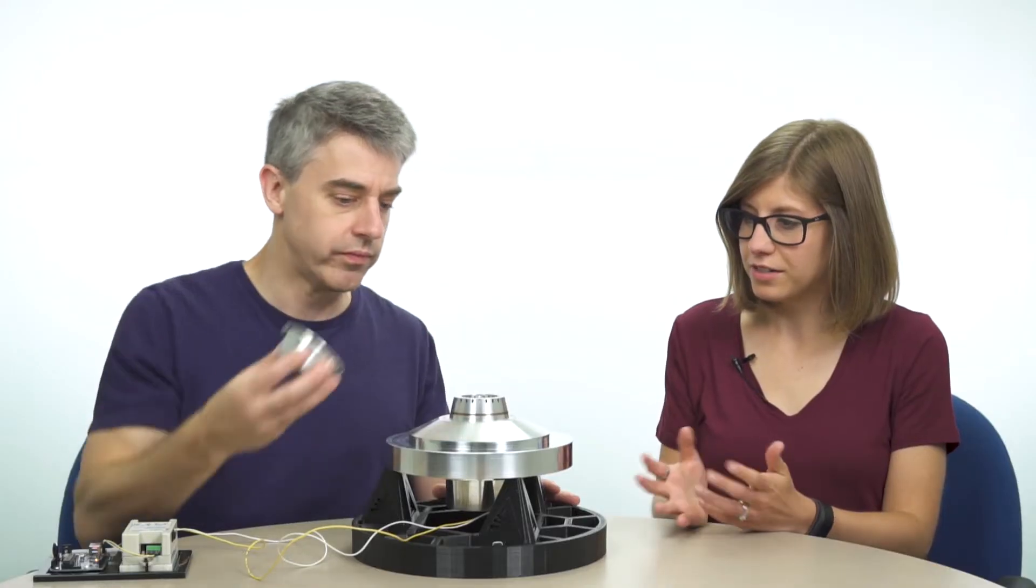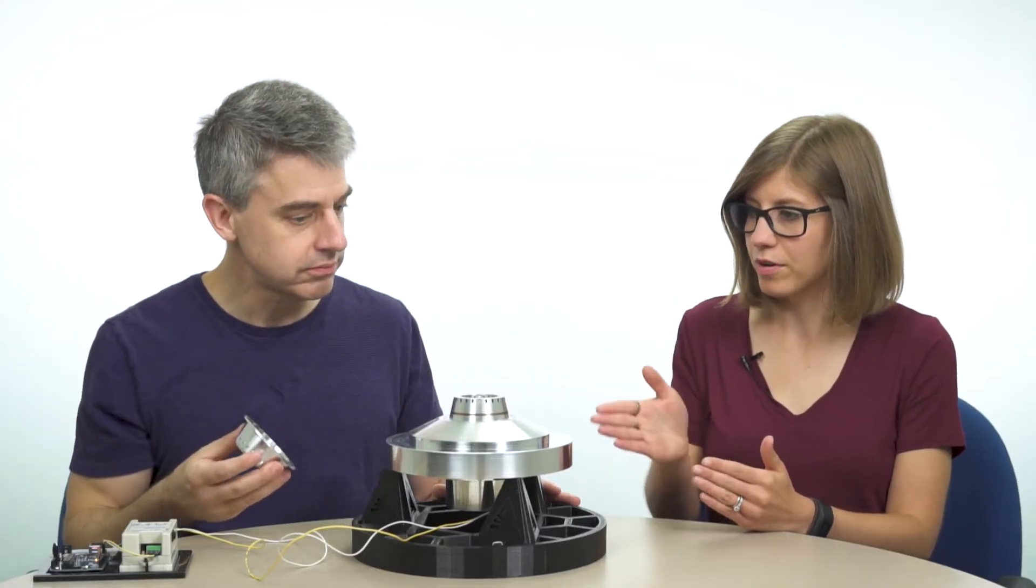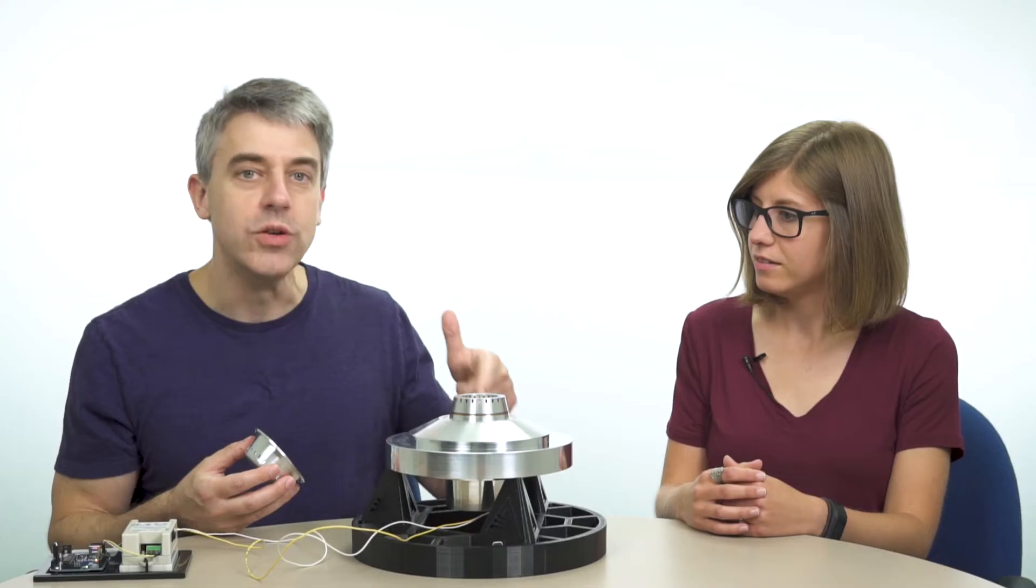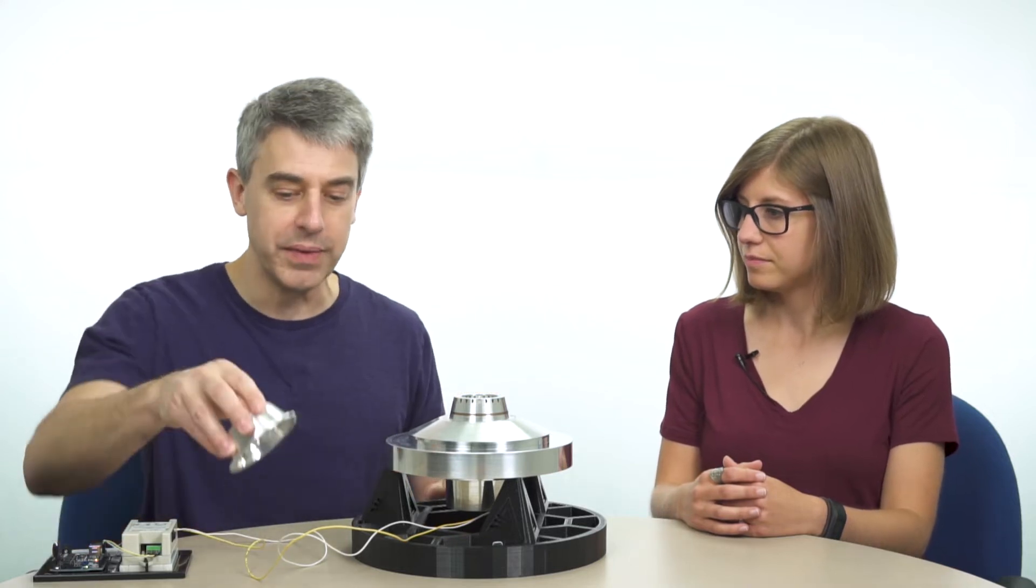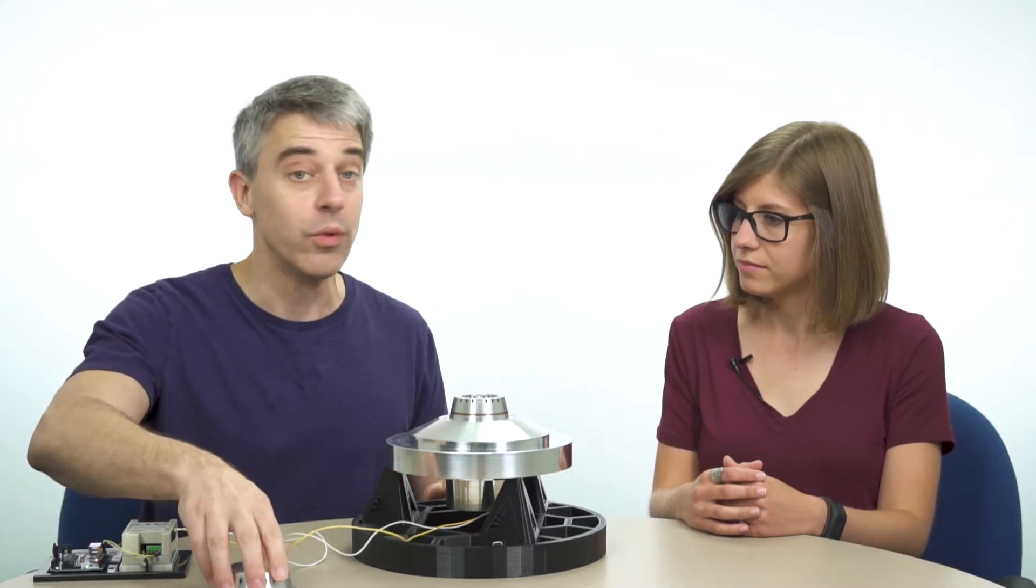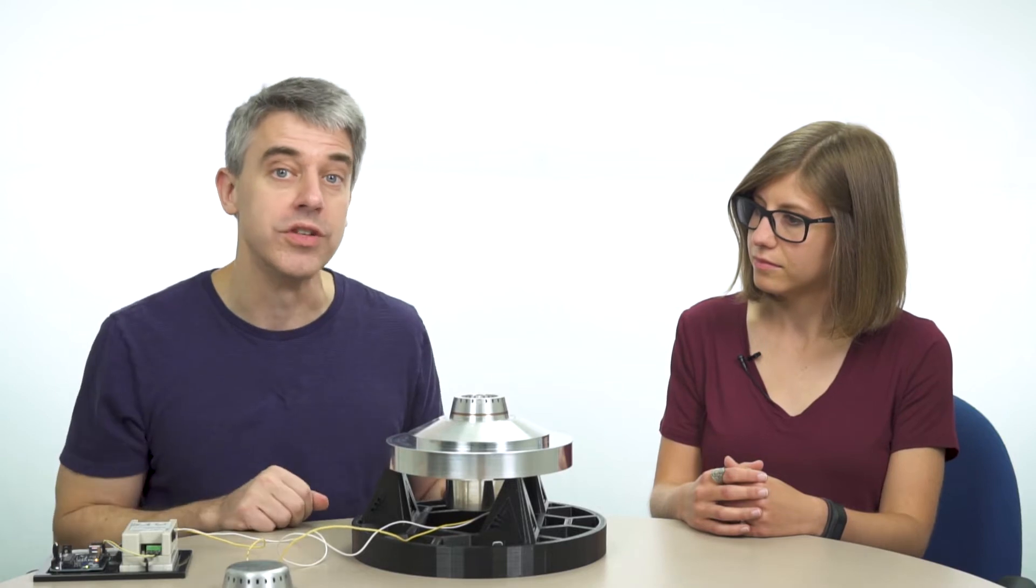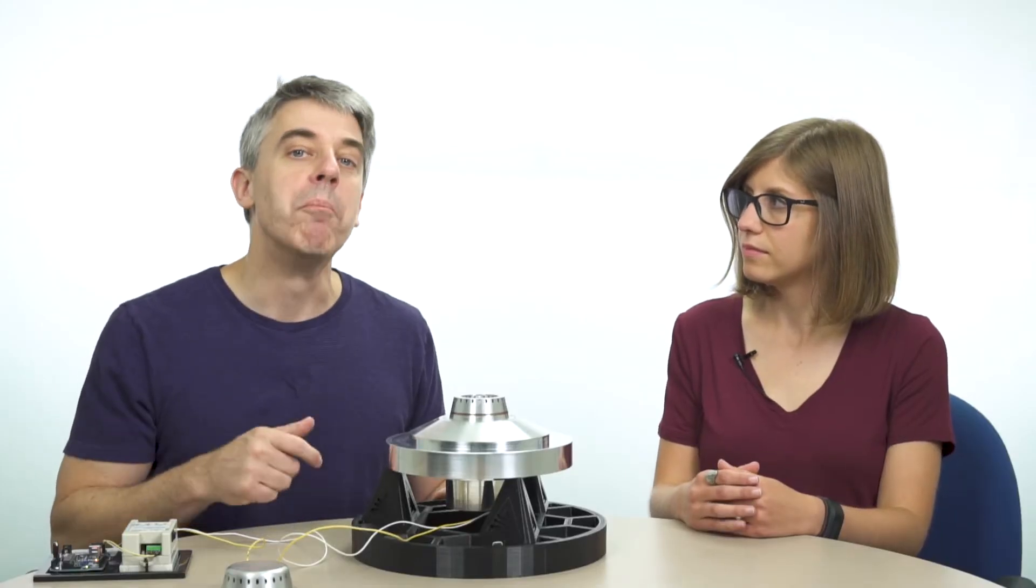So this looks pretty solid and you're saying there's a motor embedded in there. How do you get the motor in there and not damage it with metal 3D printing? This was made using a solid state additive manufacturing process. There was no melting involved, there was no high heat. The motor was never in danger. This was made through ultrasonic additive manufacturing. It was made by Fabrisonic.